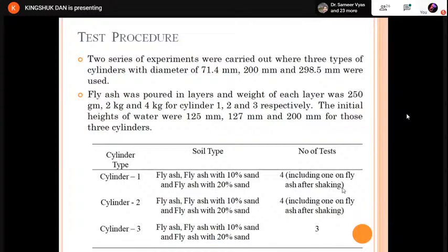When fly ash is used with 10% sand, then at first we pour 225 gram of fly ash, then 25 gram of sand is used, and it is allowed to settle for another 1 hour. Then after complete settlement, for cylinder 1 and cylinder 2 we have used 4 layers, and after complete settlement we remove it, and we remove each layer, layer by layer.